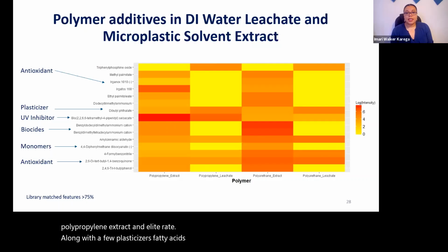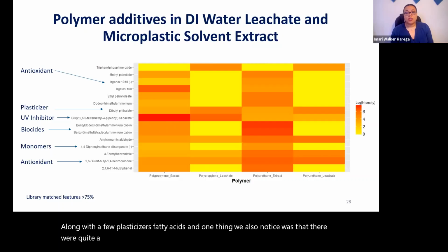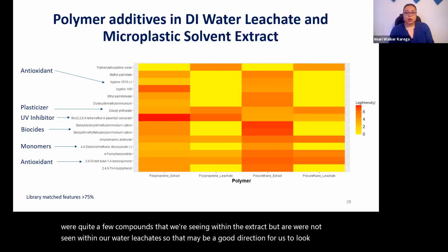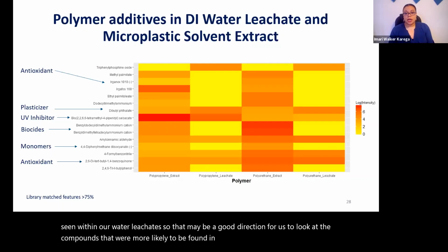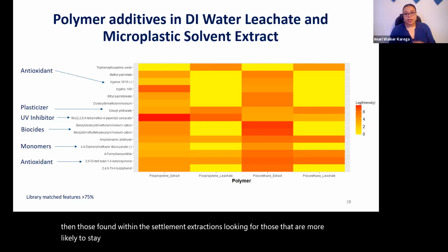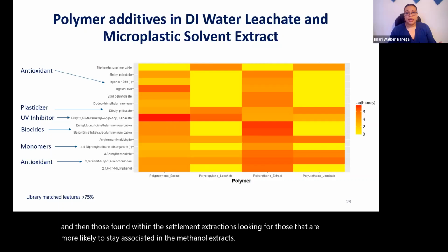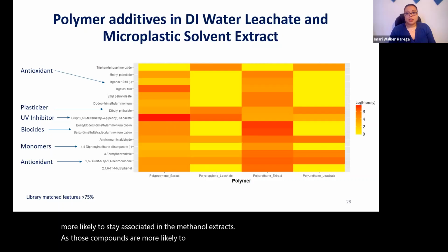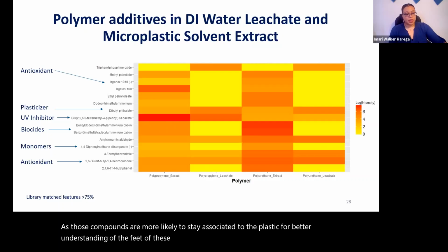One thing we also noticed was that there were quite a few compounds seen within the extract but not seen within our water leachates. That may be a good direction for us to look at compounds more likely to be found in the water for trends over time, and those found within the sediment extractions, looking for compounds more likely to stay associated in the methanol extracts, as they're more likely to remain associated with the plastic, for better understanding of the fate of these compounds and microplastics in general.